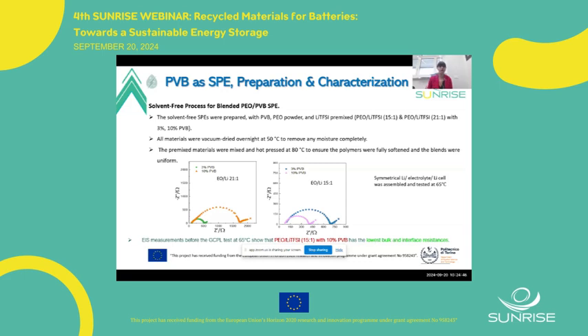Then we mixed them without any solvent, all together, followed by hot pressing at 80 degrees. Then in a symmetric lithium cell, we made some impedance measurements, as shown for PEO-lithium 21:1 and PEO-lithium 15:1.